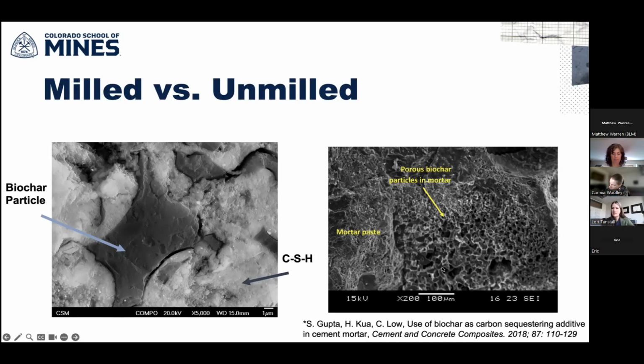But you can see when the biochar is milled, on the left side here, it's really well integrated into the cement hydration products, abbreviated here as CSH. It's calcium silicate hydrate, which is really the glue of the cement that binds everything together. When we load the samples to failure, we haven't seen any failures along the biochar line, the interface between the cement and biochar, indicating that there's a really tight bond. So that's good news for its use in concrete.